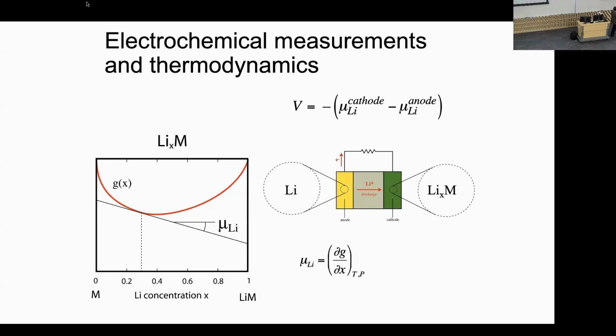then you can show thermodynamically that the voltage that you measure, and this is the Nernst equation, is related to the lithium chemical potential in this compound minus the lithium chemical potential in the anode, which if it's just pure metallic lithium, so lithium foil, is just a constant. And so what that means is whenever you measure the voltage in a cell like this, what you're really measuring is the variation of the lithium chemical potential.